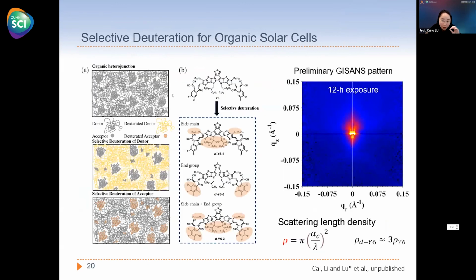So for X-ray, the contrast mainly originates from the contrast between the crystalline domain and amorphous domain. But now we are trying to use neutrons to deuterate our sample selectively, so that we can tune the contrast between donor and acceptor and understand the phase separation in the amorphous region. Our preliminary result tells us that the deuterated non-fullerene acceptor Y6 has about 3 times the scattering length density of the undeuterated molecule, which will give us significant contrast between donor and acceptor. So we can have a better understanding of the morphology inside organic films.